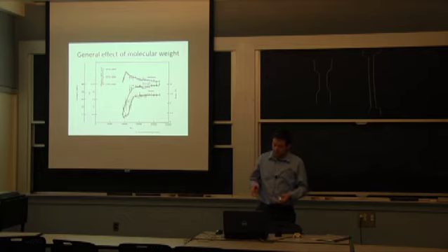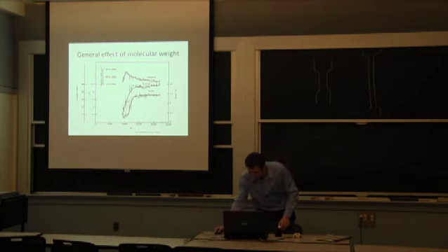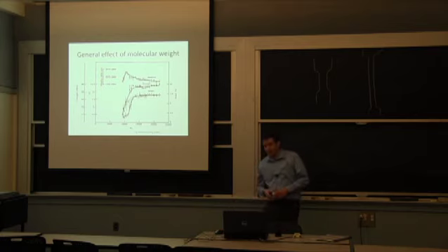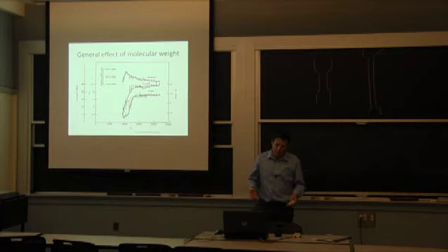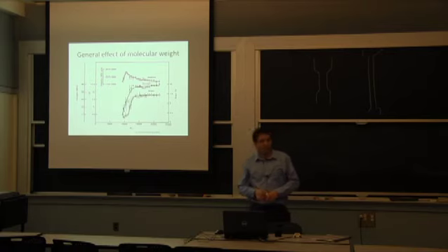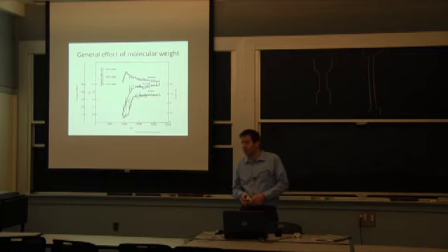So if I essentially decrease the molecular weight, going from this point here, the low point, to a higher value, I get a better modulus, and I get a better short-term strength because of how these crystallites form. I can form my crystallites more nicely. I can have more percent crystal because it's easier to put them all together. If I go to creep, I guarantee you it will be the complete opposite. The shorter molecules will be flowing more easily through the network than the longer ones. And the 40% difference in molecular weight is very significant.